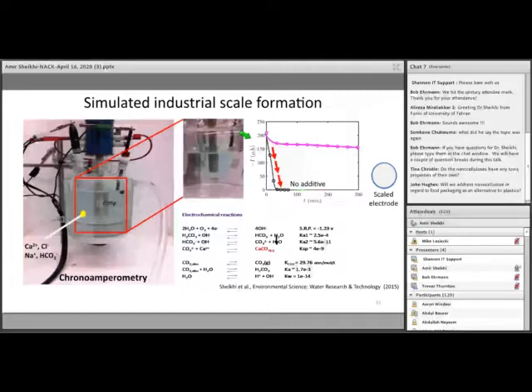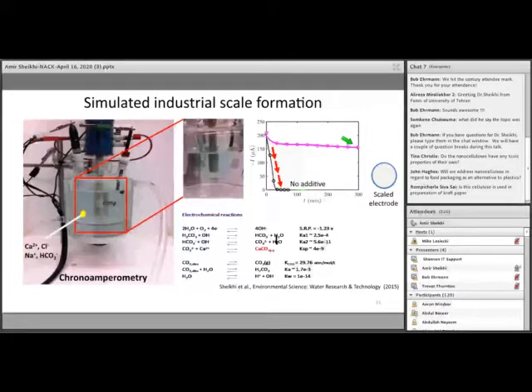Now, by applying this voltage to the electrode, what happens is that we form OH- on the electrode, which shifts the equilibrium of carbonic acid towards the formation of carbonate, which reacts with calcium to form calcium carbonate, and the scaling forms and the current goes down to 0. So in the future slides, whenever you see these figures, if the current is almost constant, it doesn't drop, it's a good sign that the system doesn't scale, and if it drops, the system starts scaling.